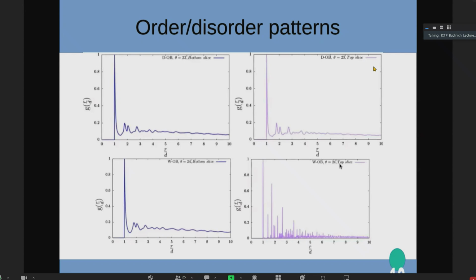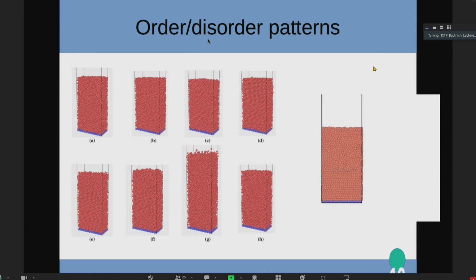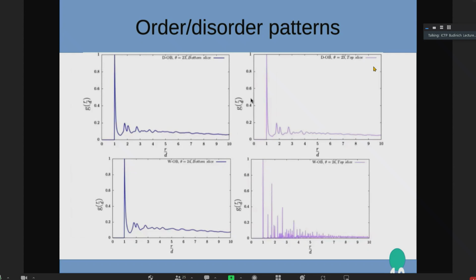For this case, we studied the structure. It was actually studied before for dry systems. We developed LIGGGHTS code to simulate granular material for wet as well, and with this package we compared the structures in dry and wet granular material. You see that here we have almost complete crystallization in dry systems for 23 and 25 degrees of the inclined plane, but for almost the same cases for the wet system, there is no crystallization, and an almost polycrystalline structure appears on top of the system.